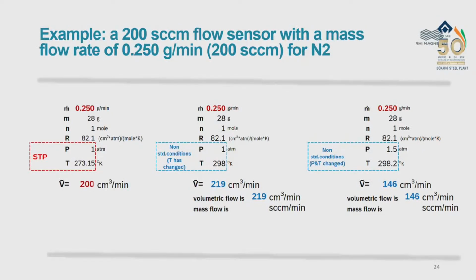So, this is the difference between volumetric flow rate and mass flow rate. See, I have this standard temperature and pressure of 1 atmosphere and temperature 273.15 Kelvin. The volumetric flow rate is 200 cubic centimeter per minute. But if I change the standard temperature and pressure to non-standard conditions, I have changed P and T both. See, the volumetric flow rate has changed to 219 and 146. But the mass flow rate remains the same, 200 standard cubic centimeter per minute. Unless and until you change 0.25, this 200 will remain the same for all the volumetric flow rates of 200, 219, 146.